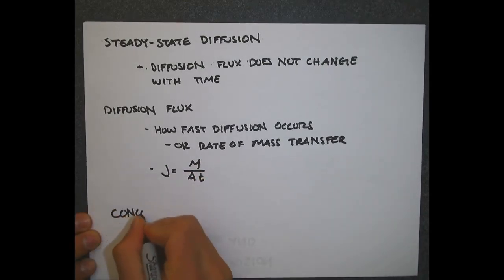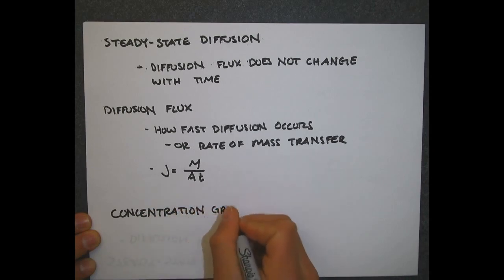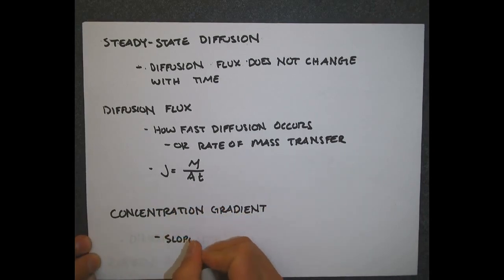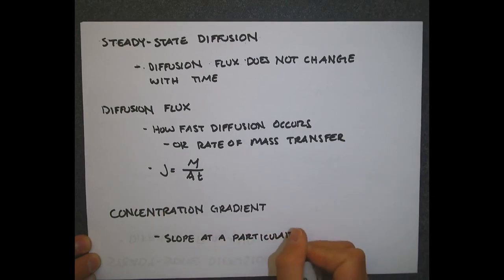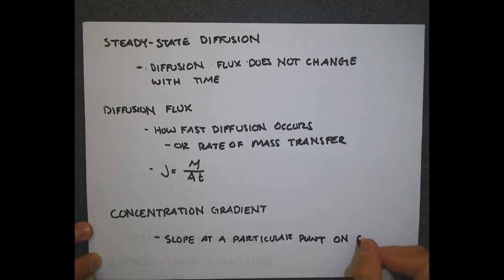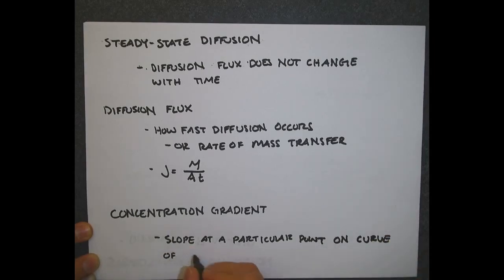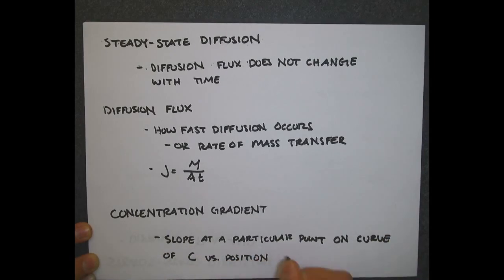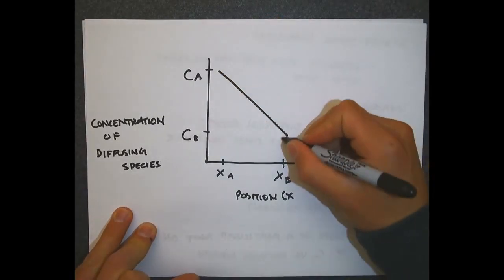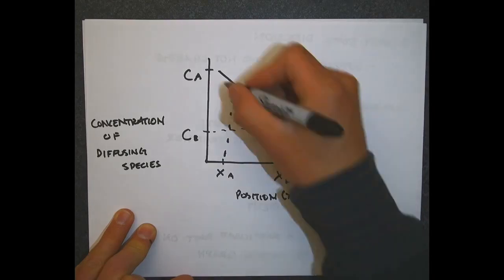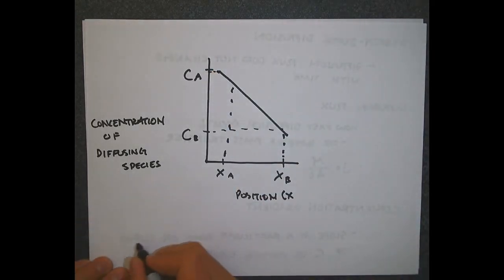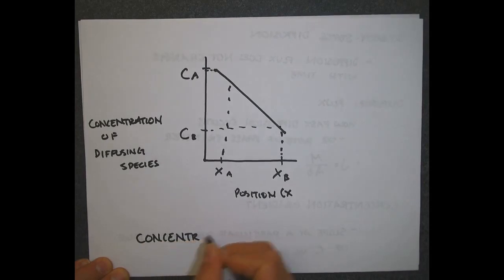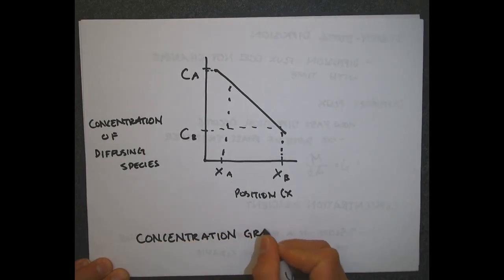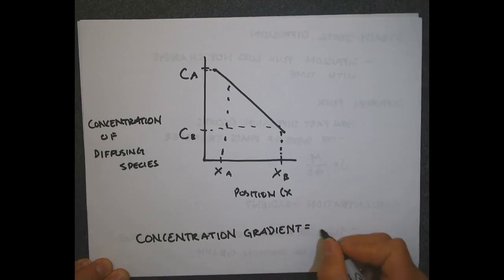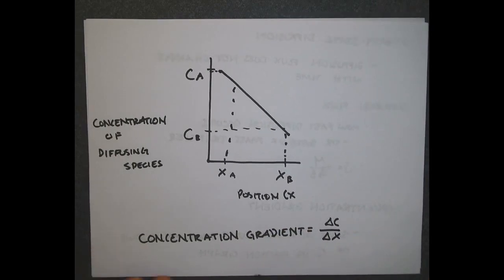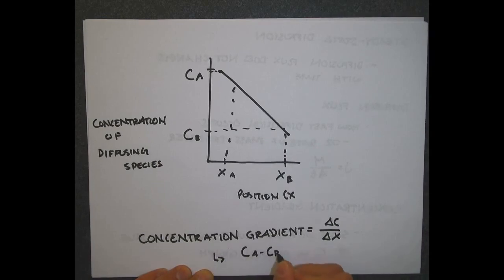Now, last thing I want to mention is concentration gradient. Concentration gradient is related to the concentration profile, except the concentration gradient is the slope at a particular point on a curve of the concentration versus position graph, which I will show you here in just 1 second. So the graph is the concentration versus position, and as you can see there's two concentrations, C sub A, C sub B, at two positions, X sub A, X sub B. So the concentration gradient is the slope of this graph, delta C over delta X, because we know the slope is rise over run, which is also C sub A minus C sub B over X sub A minus X sub B.